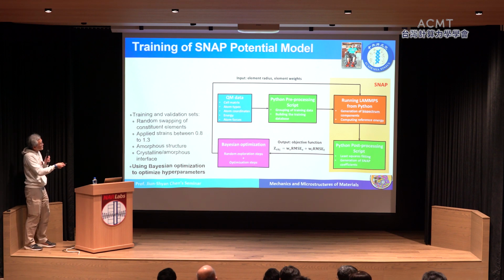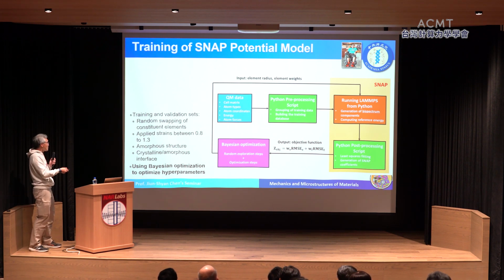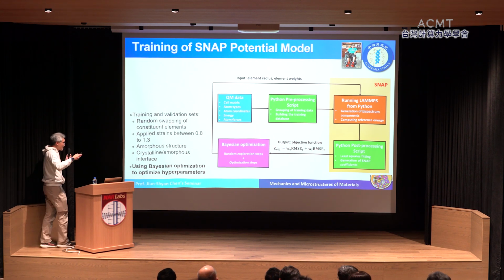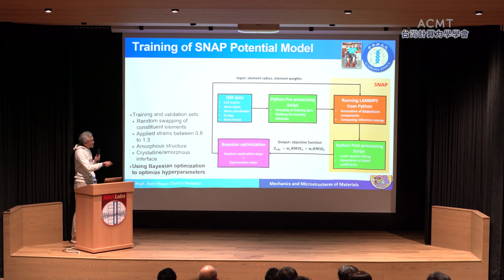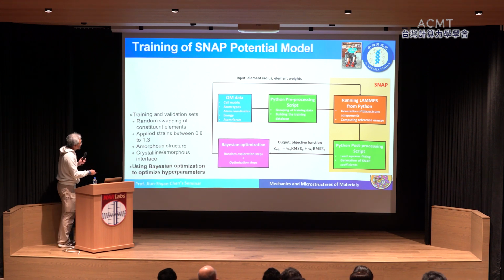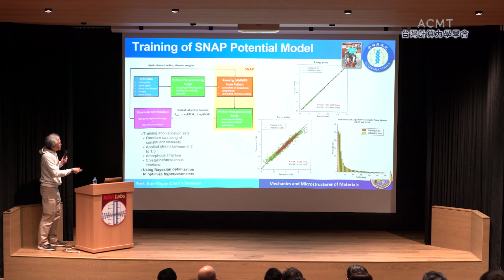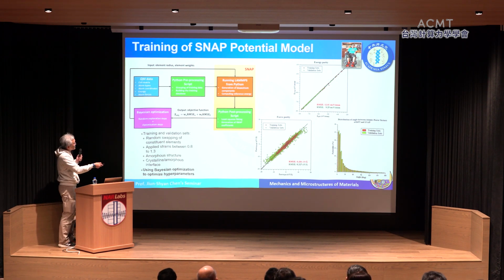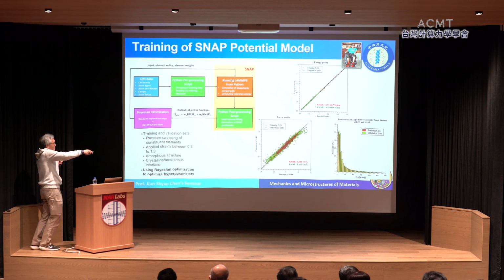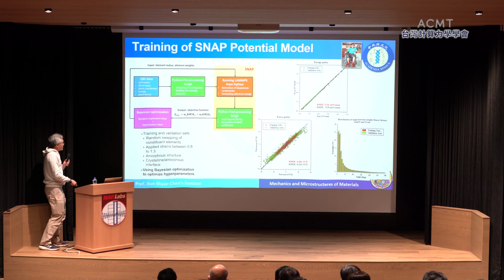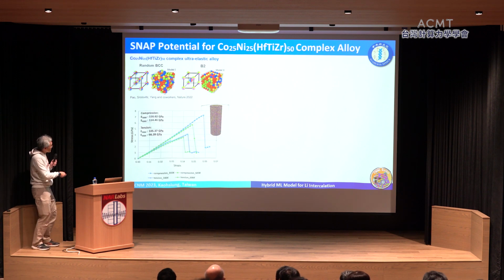This is done by my current postdoc, and this is basically the training flow. We once again start from a large set of quantum chemistry training data, and then feed all these parameters. And once again, these are the training results. This is the energy from DFT calculation, and the energy predicted from this SNAP potential model. They are in very good agreement, and this is atomic force. And with this, we can perform very large scale simulations. This result is from DFT calculation, and these are basically the size limits that allow us to use DFT. But using the machine learning potential, we can do this.